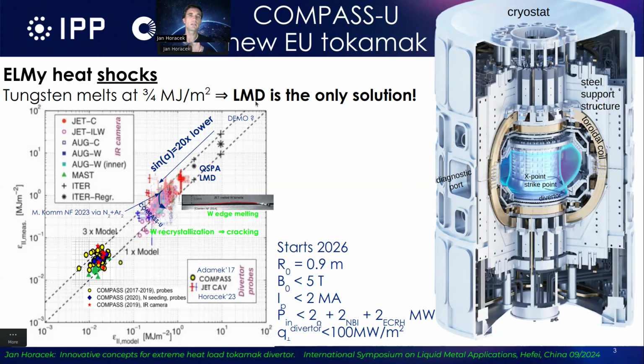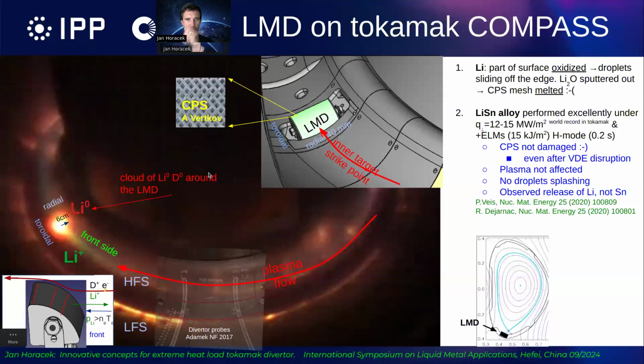We know that liquid metals can survive this. The QSPA device in Kharkiv in Ukraine was showing to survive up to 4 megajoule per square meter without any damage, unfortunately until it was damaged by the Russian army in 2022. But unfortunately, it's splashing quite a lot of tin into the plasma, which is okay for the LMD target, but it's not okay for the plasma itself.